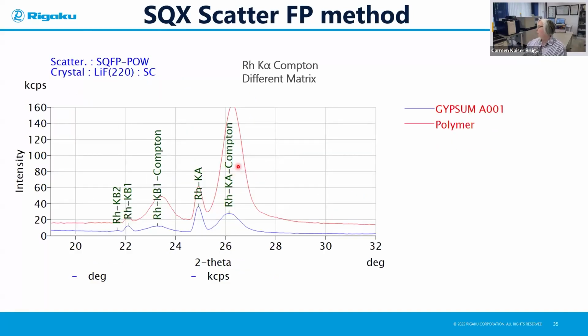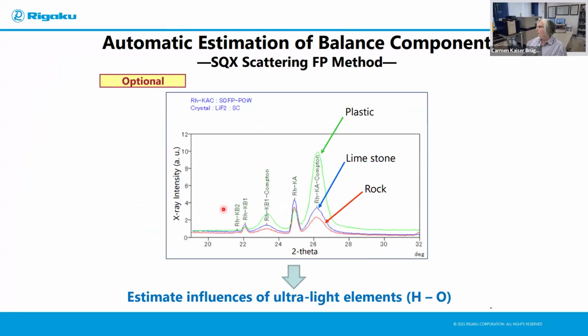Here we have another example where we overlaid the Compton line with a polymer and a gypsum. Polymer has a very, very high organic part of the matrix. Therefore we have a much higher Compton line, more intense. So our scattering FP, as you can see, which is an optional part in the software, is very useful for the analysis of materials like rocks and limestones and plastics, because this will have an influence from the hydrogen, carbon, oxygen, nitrogen portion of the material.